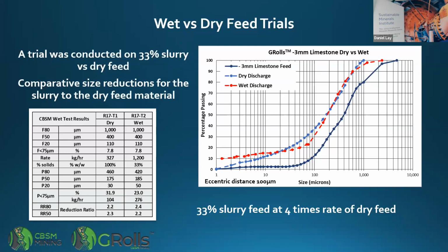And then we wanted to prove the concept that we can use it in wet, so we used the same material, a minus 3mm limestone, to basically replicate a refeed material from a mining process going into a regrind circuit, and see if we can replicate that. As you can see, the dry grading and the wet discharge were relatively similar for the same material, so we're getting quite high percentages of fines. The interesting fact was that the slurry went through at 4 times the rate of the dry feed, so it actually passed through the unit quite quickly.